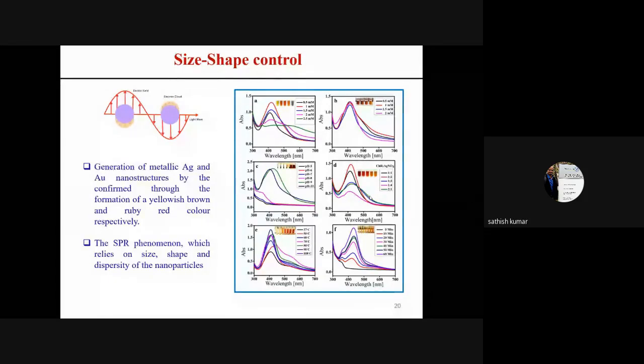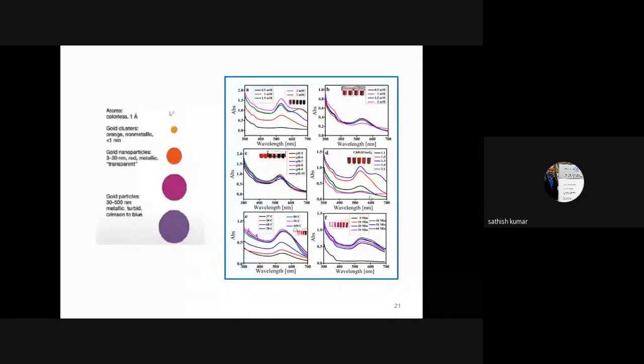Similarly, based on the color also, we can predict the size of the nanoparticle. Here, the gold nanoparticle with red color indicates that the particles are in the range of 3 to 30 nanometer, and the violet color indicates that particles are above 100 nanometer. So based on that, we can predict the size, and we can control the size of the particles. Not only for this particular reducing agent, if you are using a plant extract also, we have to fix all these optimum conditions. Then only we can get better quality end products.